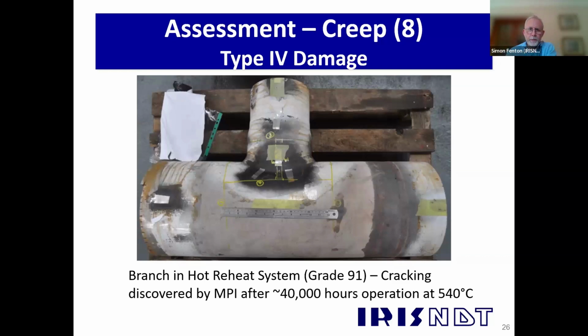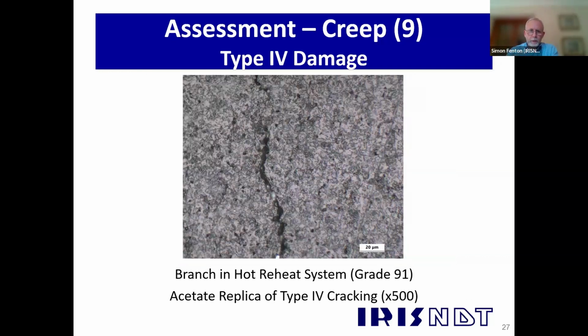Okay, next slide, please, Pete. That's the result of the replica. So this is a times 500 magnification shot, acetate replica at the crack tip. So you can see the micro crack there, but also to either side of the micro crack, you can see the little black dots in the martensitic microstructure. So those are creep cavities forming on the grain boundaries of the structure. Okay, next slide.